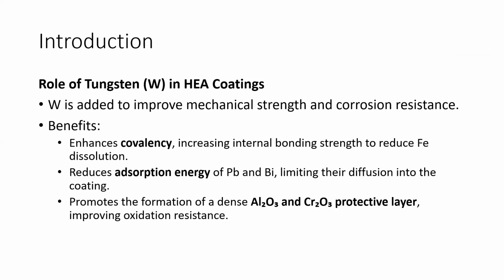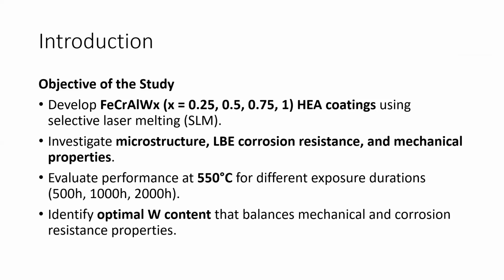The role of tungsten in HEA coating is to improve mechanical strength and corrosion resistance. The benefits are enhanced covalency, increased interatomic bonding strength to reduce iron dissolution, and reduced adsorption energy of Pb and Bi, limiting their diffusion into the coating. It also promotes formation of a dense aluminum oxide and chromium oxide protective layer, improving oxidation resistance.